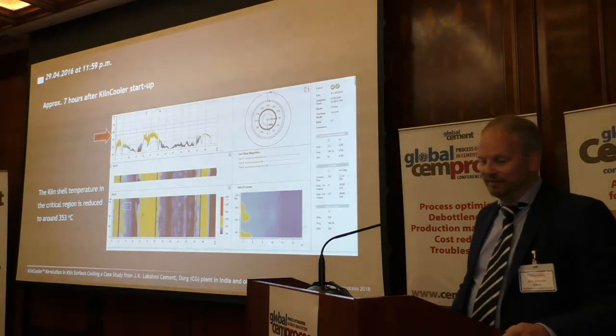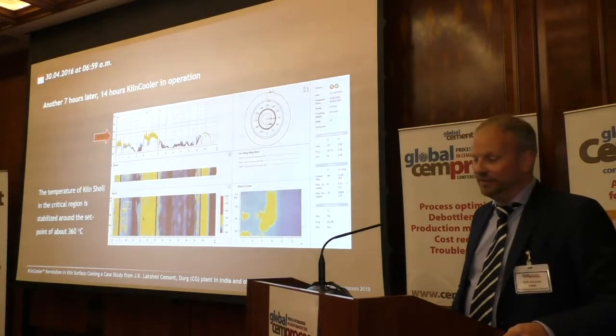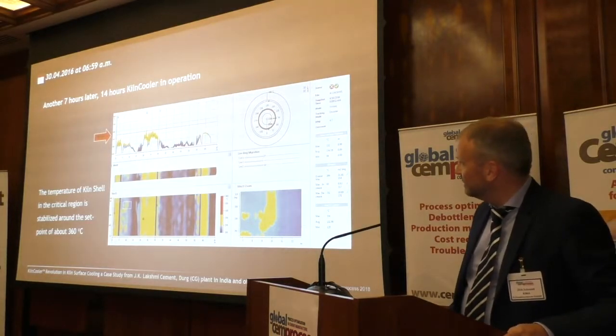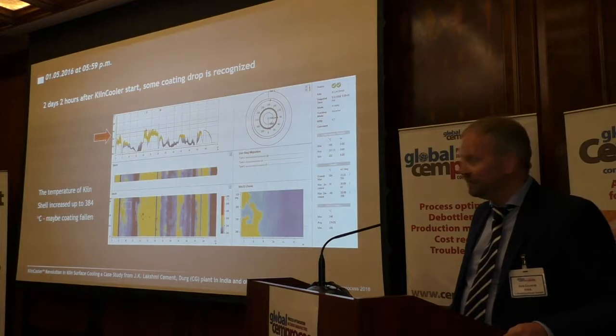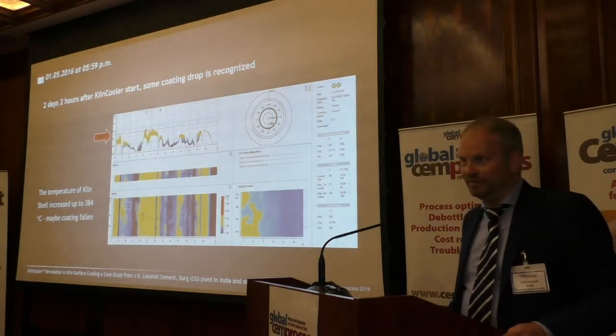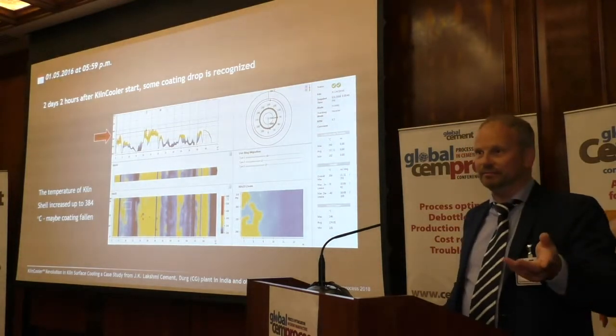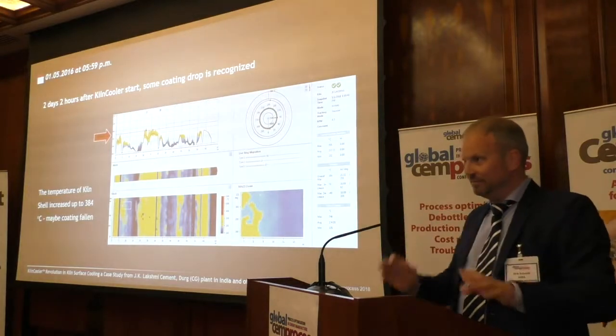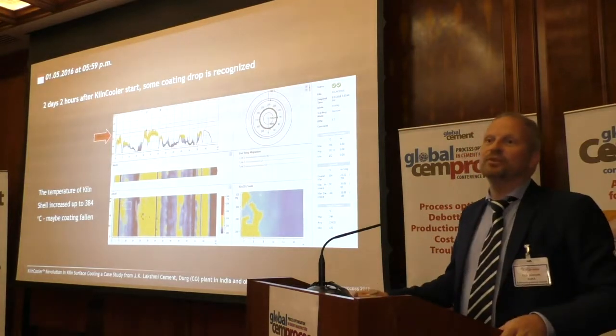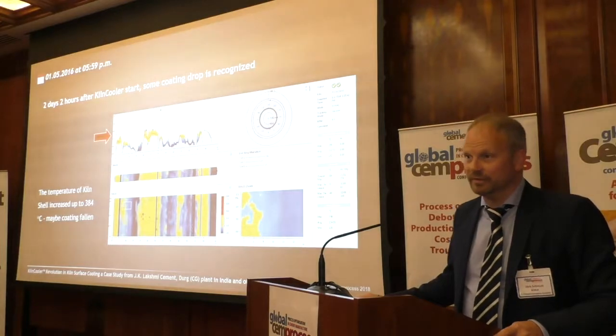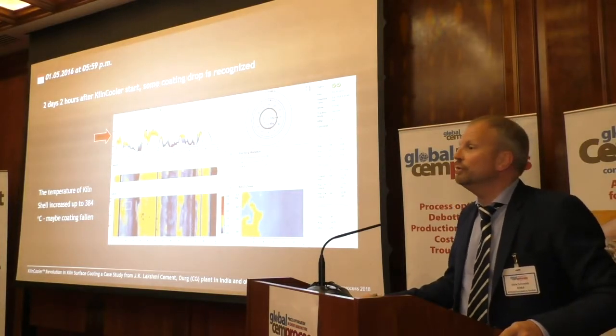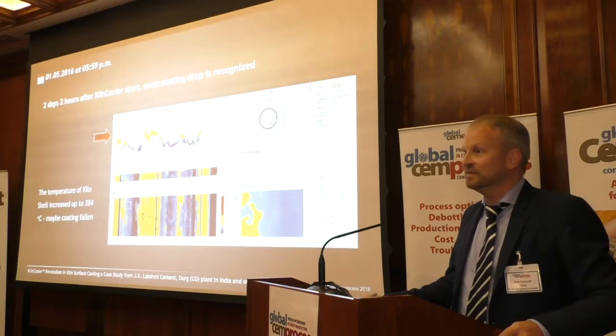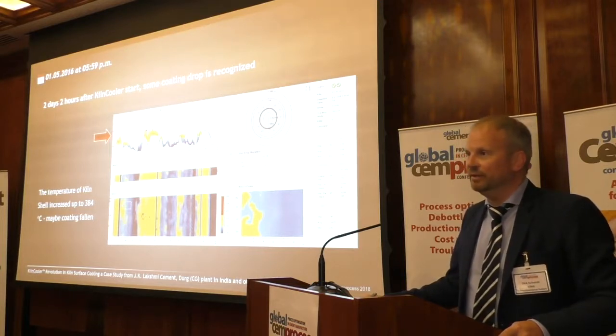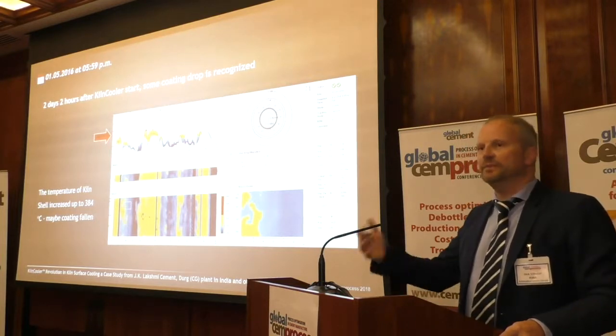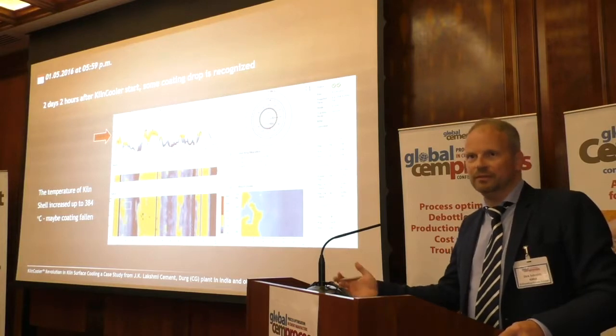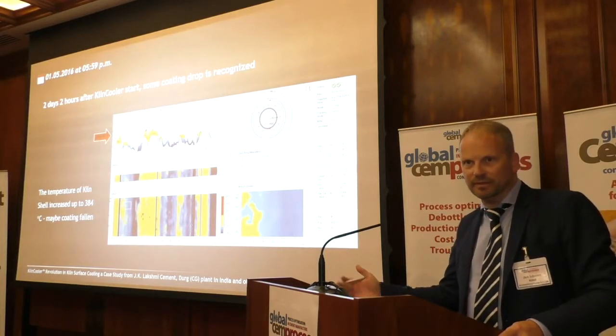So this was after 7 hours, this was after another 7 hours, so 14 hours, and this was after 2 days and 2 hours. First coating drops come again. Now, ladies and gentlemen, this system is not a miracle, or doesn't create miracles. We are not providing new refractory material into this kiln. This is impossible. However, we are able to give sufficient time and to prevent your kiln from damage.